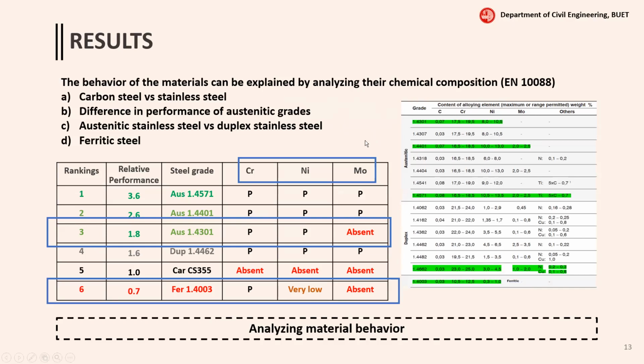We know that in stainless steel, there is the presence of chromium, nickel, and molybdenum in a controlled manner, which is absent in carbon steel, so it performs better. The difference between the austenitic grades is that the least performing grade, 1.4301, has no molybdenum, which was present in the other two. The difference between duplex and austenitic lies in the nickel and molybdenum content of each of the two. In ferritic, there is almost no amount of nickel and molybdenum was fully absent.